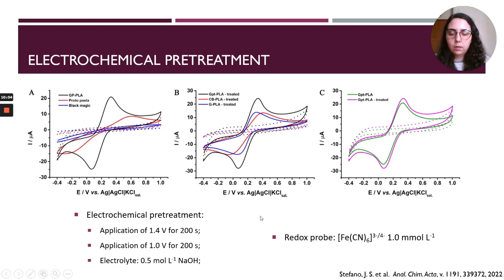And the redox probe used in these CVs was ferrocyanide. You can see from the voltammograms that without treatment, so this is voltammogram A, without any pretreatment, the performance of the developed filament shown here in black is much superior to the commercial filaments without any treatment. After treatment, we can see that the developed filament is still superior, so we have higher peak currents than the commercial ones, but you can see that there is a clear improvement in its performance.